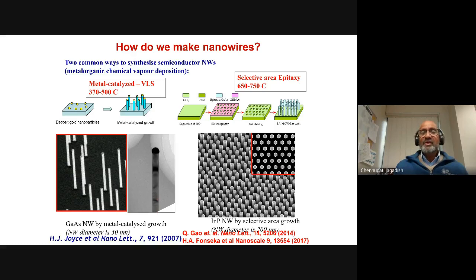And showing that we're able to really show these gallium arsenide nanowires, 50 nanometer diameter. You can see the gold nanoparticle is sitting on the top. Essentially, you can make the nanowires as small as 20 nanometers we have done, and up to 300 nanometers, essentially changing the diameter of the gold nanoparticle which you're using. So really, depending on what applications you have, you choose the right diameter of these nanowires, and I'll come back and share with you what type of diameters are needed for solar cells and lasers and others.